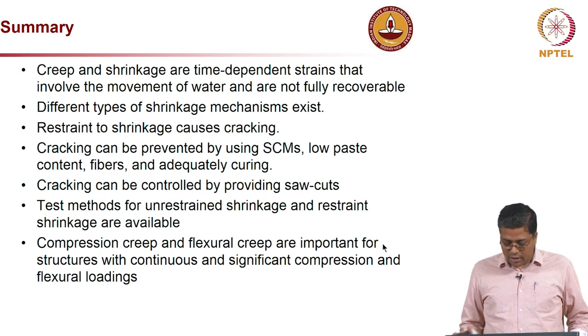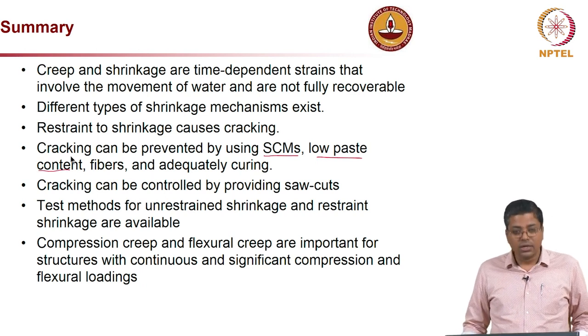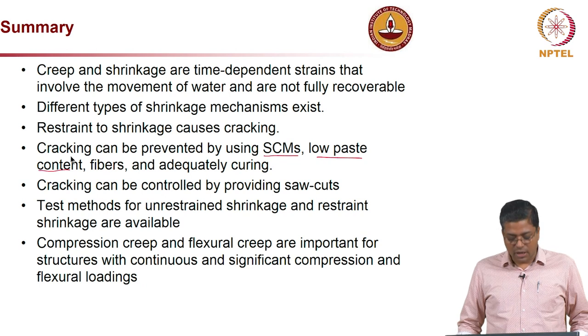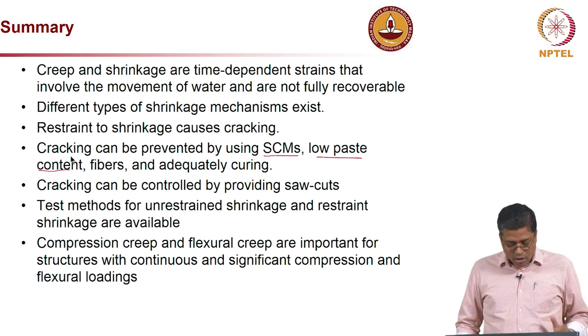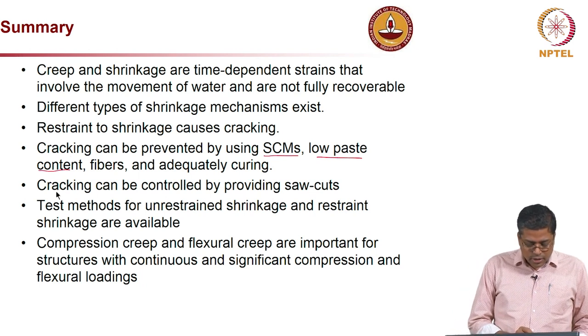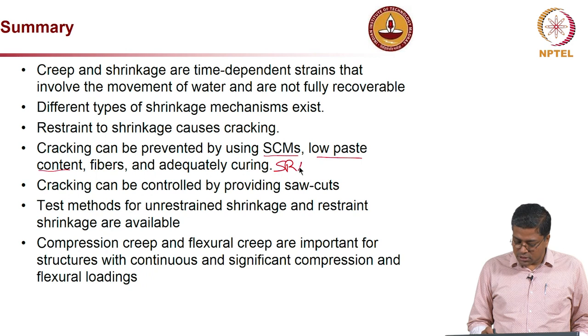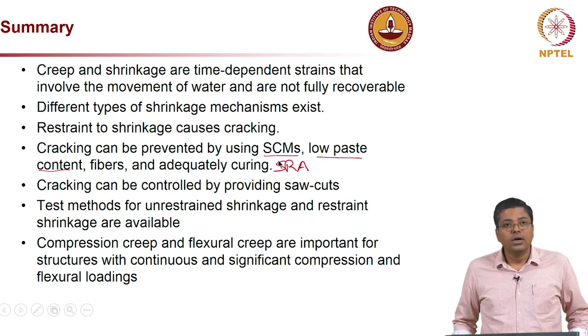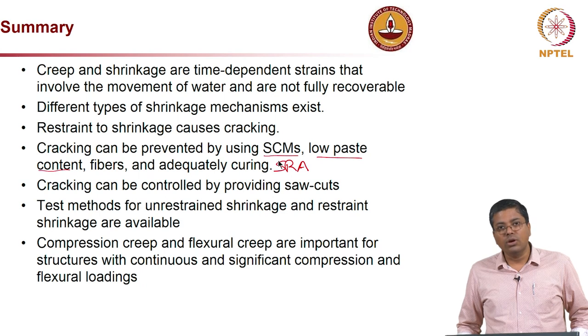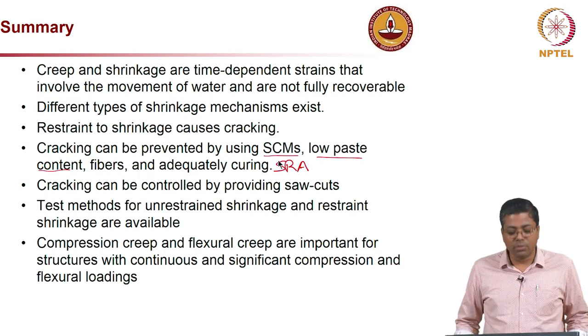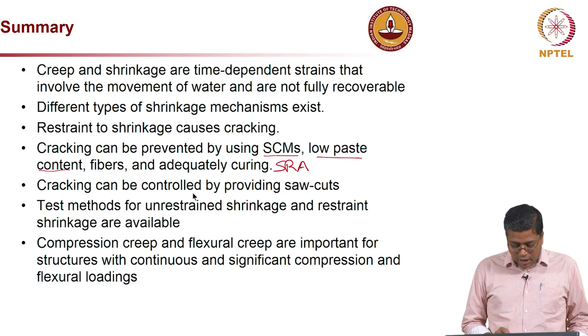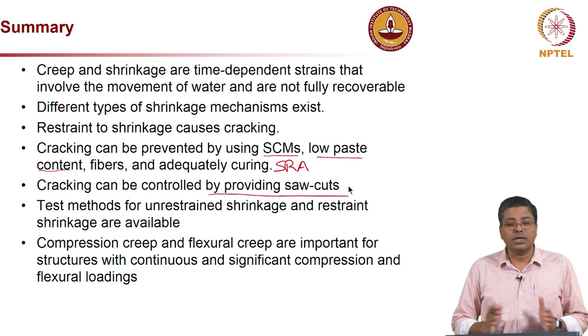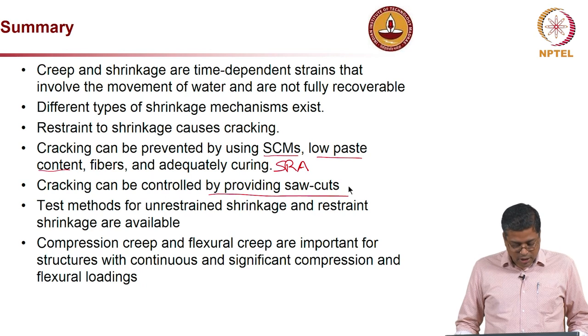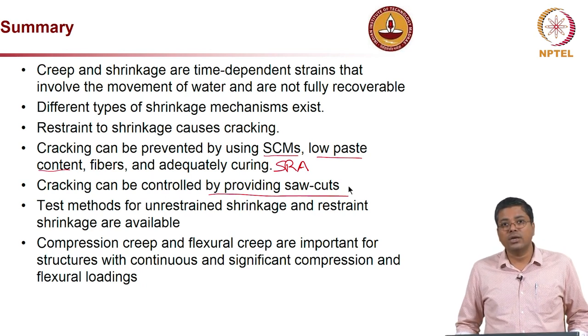How do we prevent cracking? Maybe by using SCMs, or low paste or cement content, use of fibers, and definitely by adequate curing. Also shrinkage reducing admixtures can be used, I forgot to mention that in this bullet. And cracking can be controlled, not eliminated, but controlled, by providing saw cuts at definite distances, and then test methods for unrestrained shrinkage and restrained shrinkage are available.